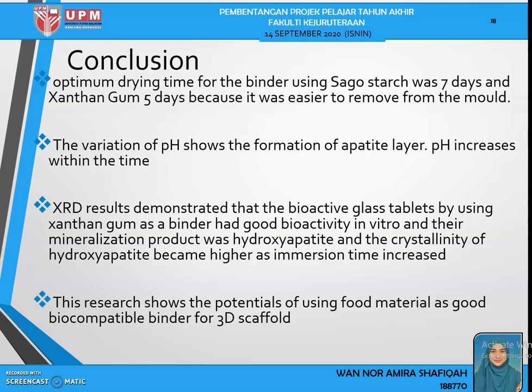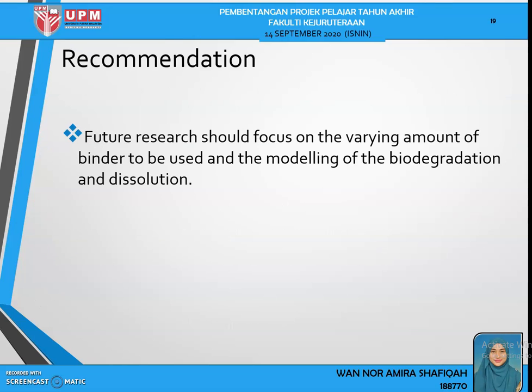XRD results demonstrate that the bioactive glass tablets using xanthan gum as a binder have good bioactivity in vitro, and their mineralization product was hydroxyapatite. Because we can see before this, the peak is high compared to the others. So this research shows the potential of using food materials as good biocompatible binders for 3D scaffolds.